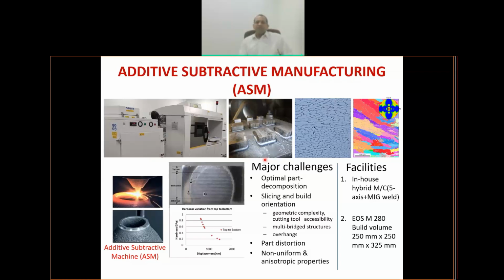And one of them is, for instance, very complex internal structures. If you want to create internal structures, there is no way that you make a solid block and then create those internal structures. So that is something which is not possible by any other means but additive manufacturing. The other thing which is possible through additive manufacturing, which is not possible through conventional manufacturing, is that you can create a set of alloy systems which are non-equilibrium. Now, you will be studying equilibrium phase diagrams. You may have done some parts of Raoult's law, Henry's law, and there are lots of very complex multi-phase systems which you can have in alloys. But almost all those alloy systems are essentially either equilibrium or metastable equilibrium phases. Whereas in additive manufacturing, you can suddenly create materials which are not really in equilibrium phases.